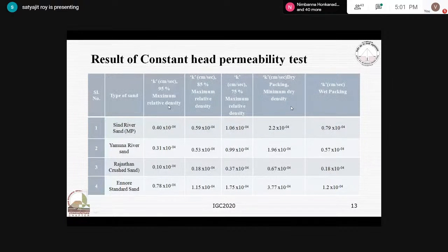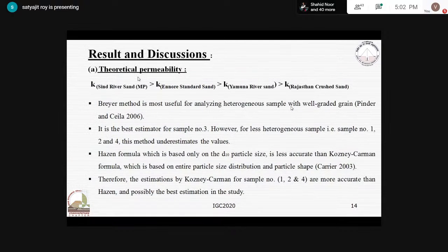Now this is the result of the constant head permeability test. I have compacted the specimen at different relative densities, like 95% of maximum relative density, 85% of maximum relative density, then 75% of maximum relative density. One is dry or loose packing, and one under wet condition. These values all come in the range of 10 to the power minus 4, minus 5, and minus 3. But the theoretical permeability values are in the range of 10 to the power minus 1 to 10 to the power minus 2 centimeter per second.